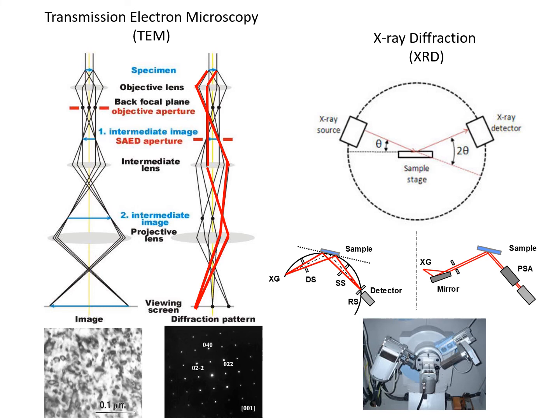In TEM, we're using scattering from a sample. We have a sample at this level. Here we shine electrons through it, and in the case of electrons, the beauty of electrons is that they're electrically charged, obviously, and because of that, you can use electromagnetic lenses to basically focus, distort, affect the refractive index through which these electrons are passing.